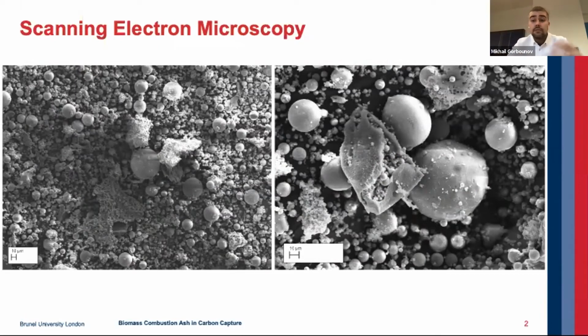In any case, as can be inferred from the slide, the fly ash consists of a mixture of spherical particulates with a widely varying size, agglomerations of these particulates, and some porous particles as well. The spherical particles are typical for fly ashes and can be attributed to their amorphous coating formed as a result of relatively abrupt cooling post-combustion. And as clearly demonstrated on the image on the right, the various particles present in the fly ash are not uniform, and there are stark differences in them. But still, you can see a bit of porosity there.